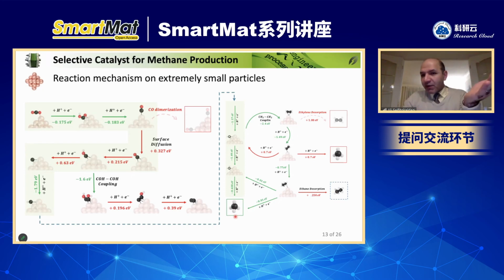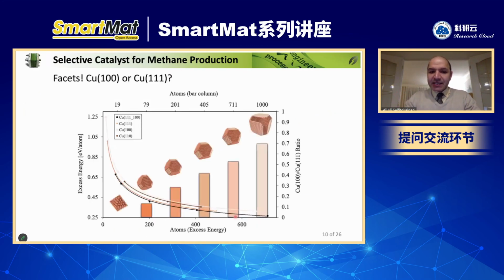One way to examine which one is important, the particle size or the facet, is, for example, synthesizing particles with very small size but with different facets. This was my question always for my PhD student. I was telling him, can you synthesize the same particle with the same size, but with 100 facet? If we are able to synthesize that particle and run the same experiment, and we observe again a lot of methane, no ethylene, then we will conclude that the particle size is important, not the facet. But unfortunately, we are not able to synthesize it.